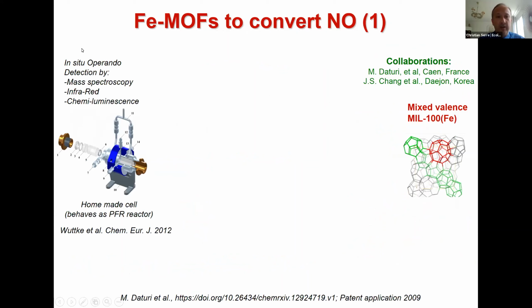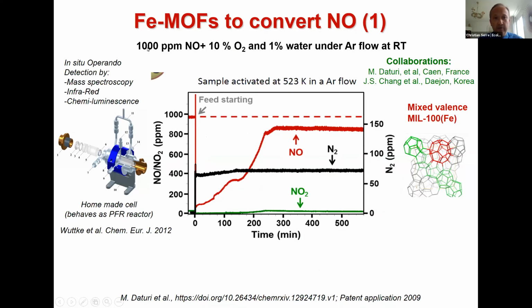This material was studied by in situ operando techniques. They used a homemade cell reactor, and the detection was ensured by three techniques: mass spectrometry, infrared spectroscopy, and chemiluminescence. They used the mixed valence iron MOF, and here is the first result. They used 1000 ppm of NO, 10% oxygen, and 1% of water at room temperature. Here you have the feed of NO, and initially you have absorption of NO into the porous solid, so the concentration of NO decreases, and then it reaches a steady state. You see almost 15% difference between the baseline and the final concentration of NO, and at the same time you get a little bit of NO2, but importantly you form around 70 ppm of nitrogen.